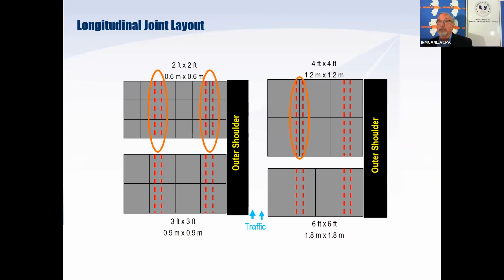as a rule, if the overlay thickness is in inches, the corresponding joint spacing is in feet, a 1-to-1 mapping. 2-inch overlay, 2x2 panels. 3-inch overlay, 3x3 panels, and so on. But what you want to avoid at all costs is putting a longitudinal joint in the wheel path. As you can see in the upper right, the 4x4 panels will put that inner wheel right in the wheel path, so you need to adjust your joint spacing to accommodate that.